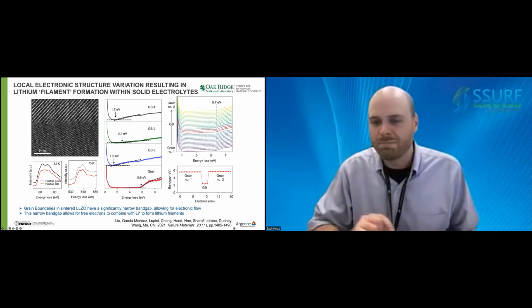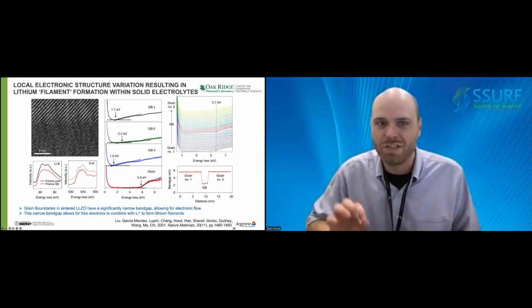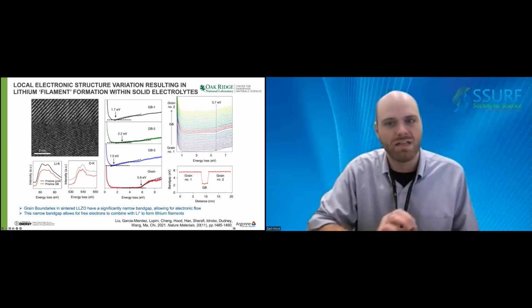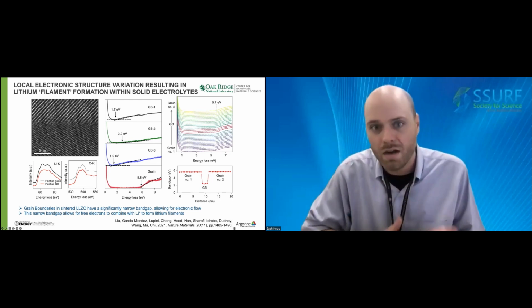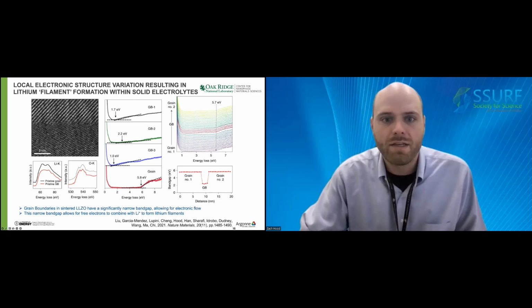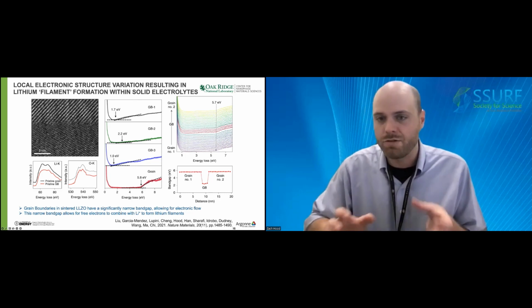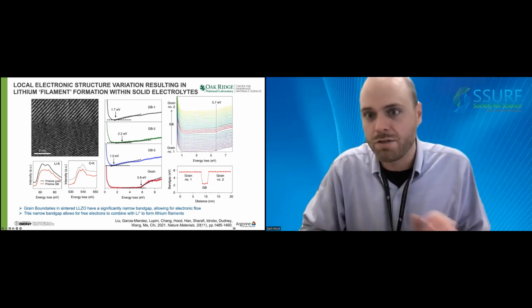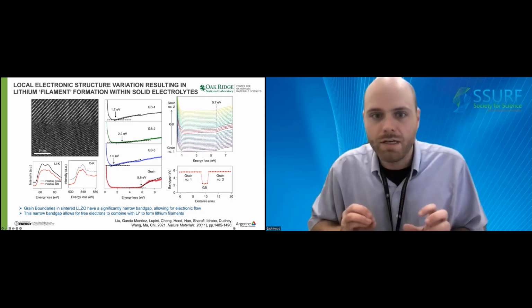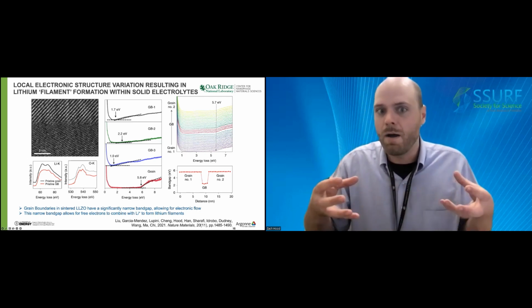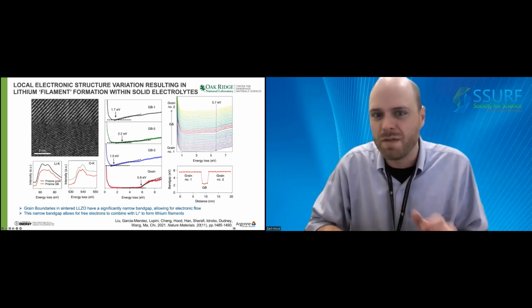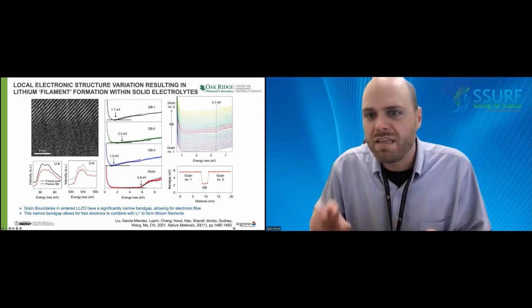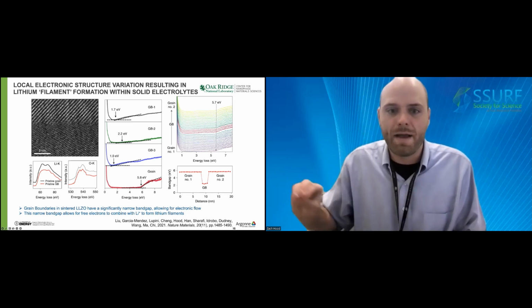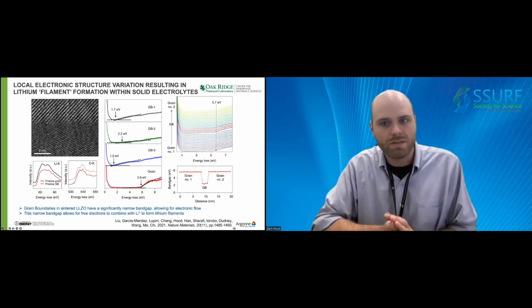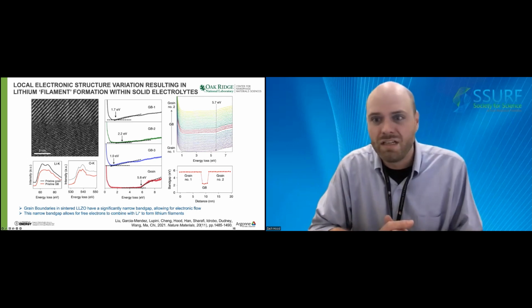But for many examples of these materials, little is actually known regarding the exact chemistry and electronic structure of the grain boundaries. When considering the oxide-based solid-state electrolytes, again, the lithium garnets that I mentioned earlier, grain boundaries are present when we make these materials and sinter them into a dense ceramic. However, the influence of these grain boundaries on the macroscopic electrochemical performance was largely overlooked in the literature.